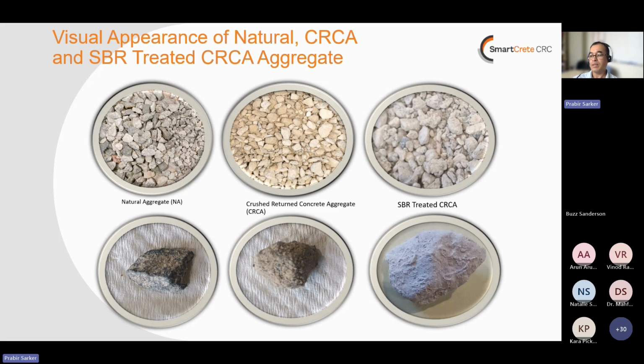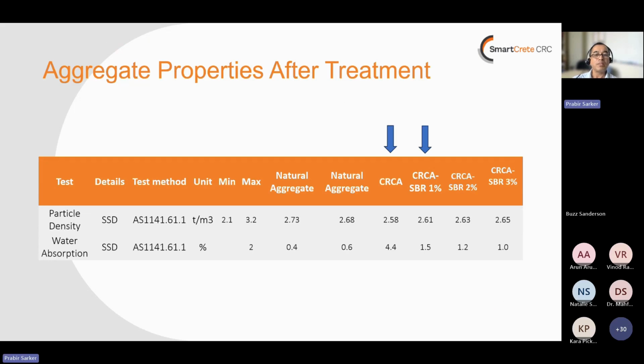But this is a very controlled way of treatment. So we cannot expect all the aggregates to be covered like this, but this is just to show what can happen to an aggregate if it actually gets coated fully by the latex. So the aggregate properties after the treatment. We can see the CRCA, again, particle density 2.58 without treatment, and with 1% SBR it improved to 2.61, and water absorption improved from 4.4% to 1.5%. So which is a great improvement that can be achieved by using the SBR latex as a method of treatment.